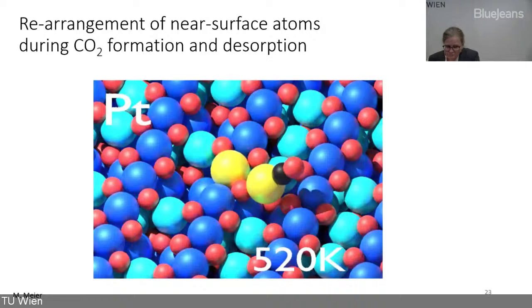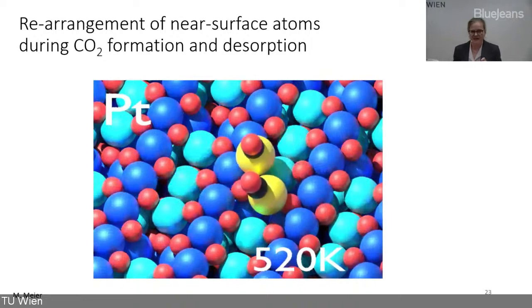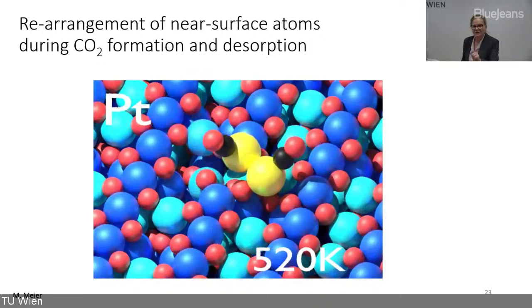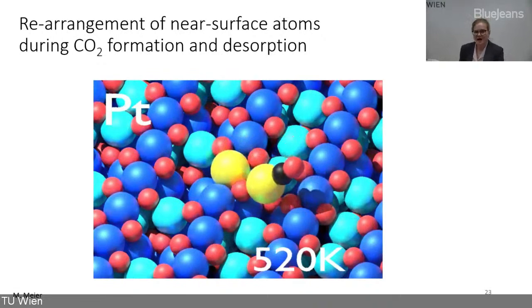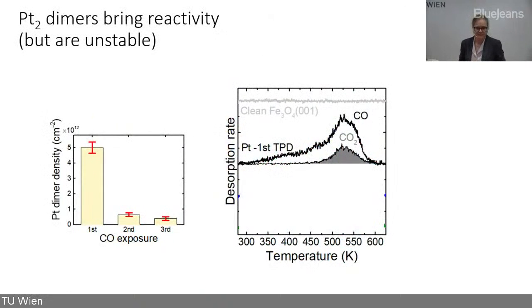Now I want to play this movie again, and this time I want you to pay attention to the surrounding of these platinum dimers, because you can clearly see how the substrate reacts, how the iron oxide reacts and changes, making one oxygen atom reactive, and that's the one that then desorbs. So it turns out that these platinum dimers bring reactivity. In the CO2 TPD trace I showed before, we saw carbon dioxide desorbing at a temperature consistent with this theoretical model we developed.